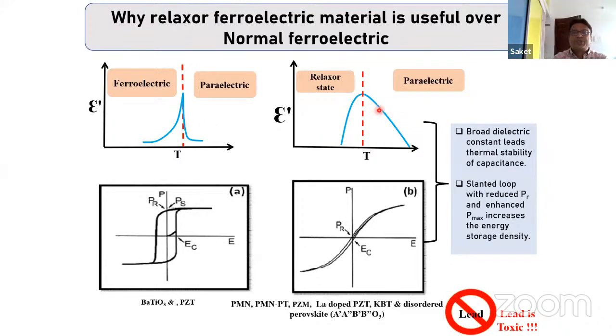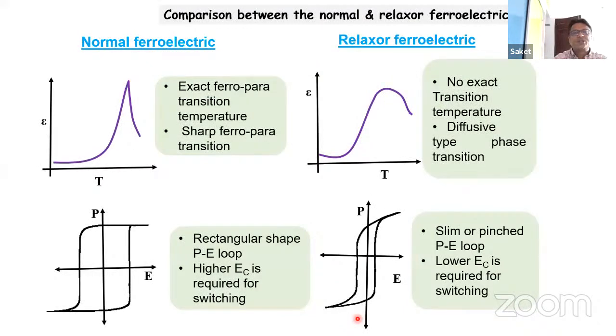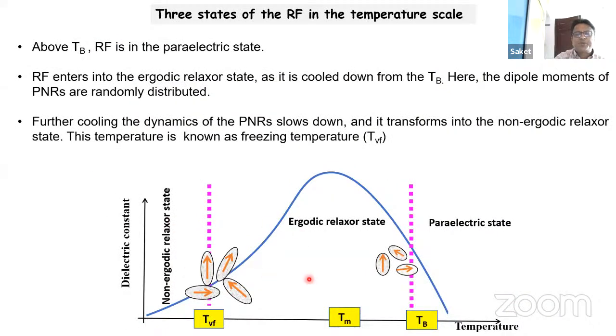Now here, if you see, this transition is diffuse. It is not very sharp. So in the relaxor state, it's not very sharp, and this transition is also frequency dependent. If you change the frequency, this maximum temperature will also shift. And the polarization behavior is like this. There are some typical materials. So here you see the transition is diffuse. Just for the clear picture, I mentioned this, and then there is some theory behind that.